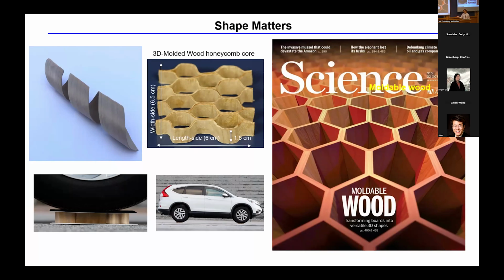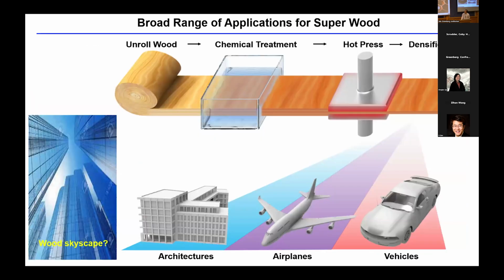Right, so when the temperature is above the glass transition temperature, you can mold plastics, at least for thermoplastics. But the same thing for wood. With the right combination of the lignin and the water content, you can mold it any way you want. And then, of course, you can fix it when you remove the water. And if you want to lock it forever, then you can do a further treatment, incorporating some polymers here.